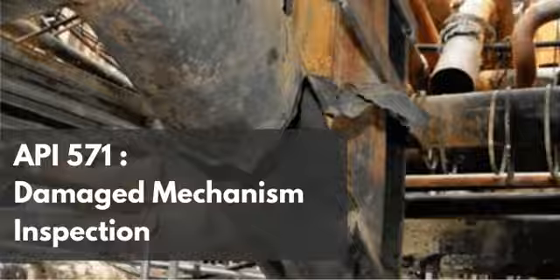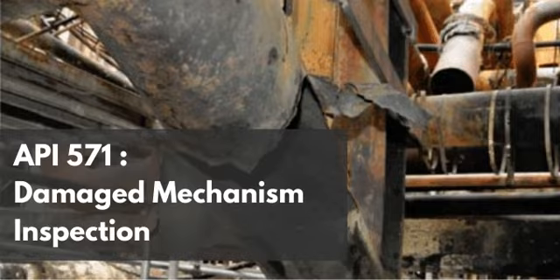You get all those eddies. Yes, you create shear stress against the pipe wall. That high velocity and turbulent mechanical energy continuously strips away any marginal protective scale that might be trying to form. It's literally tearing the scab off the wound before it can heal. That is exactly what is happening. By constantly stripping away that scale, you are exposing fresh, bare, highly reactive iron to the corrosive amine continuously.